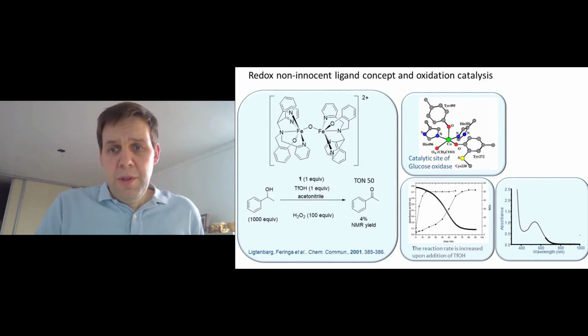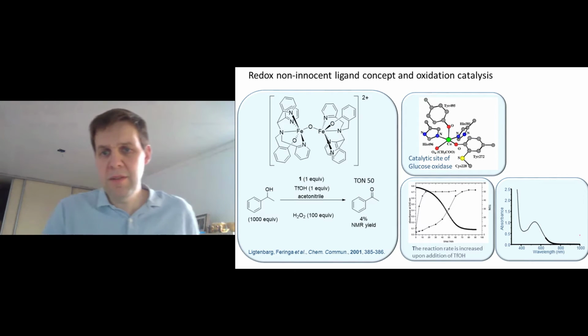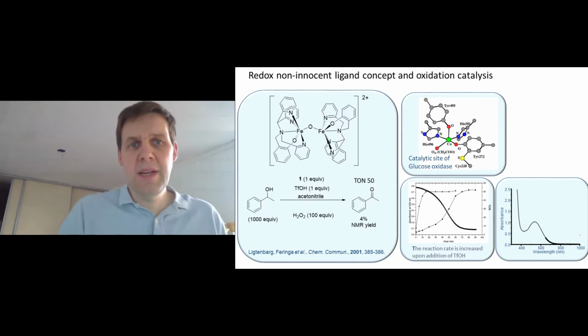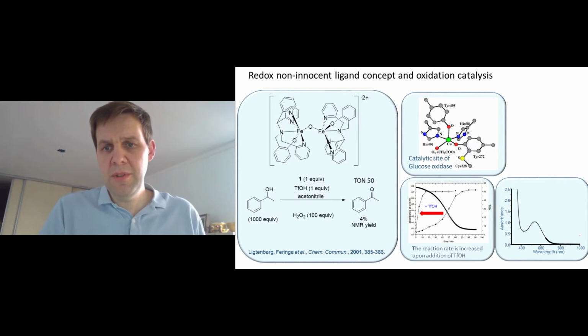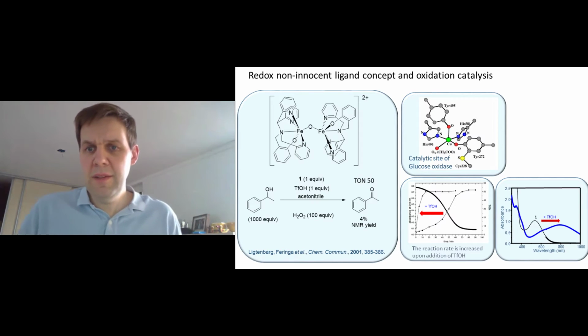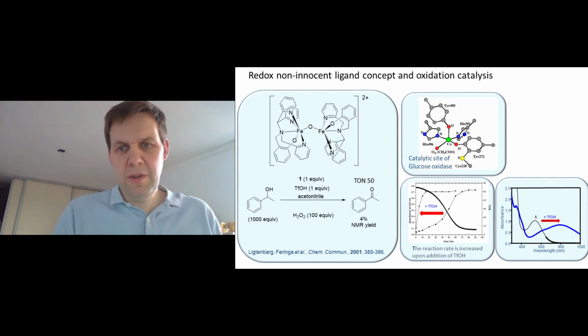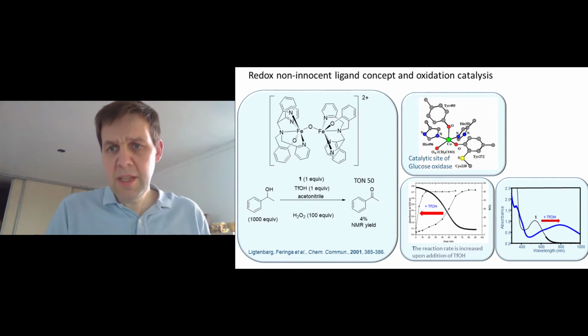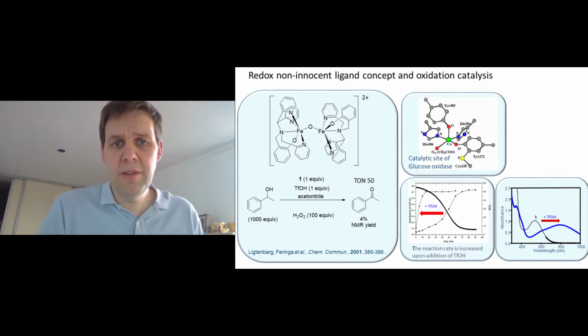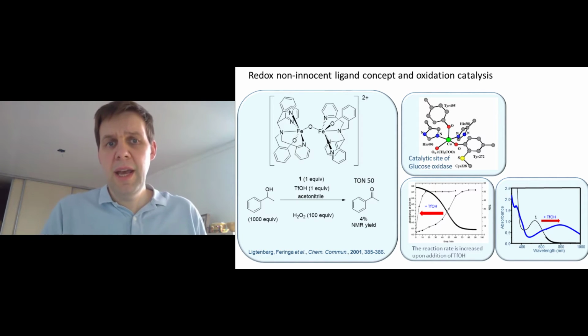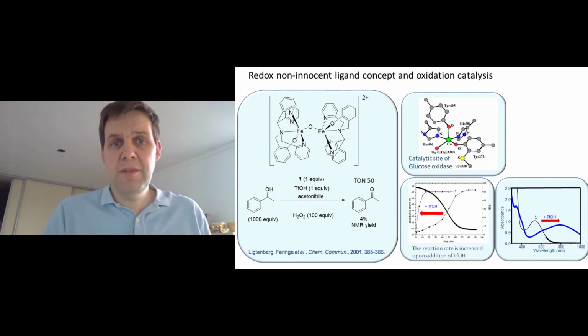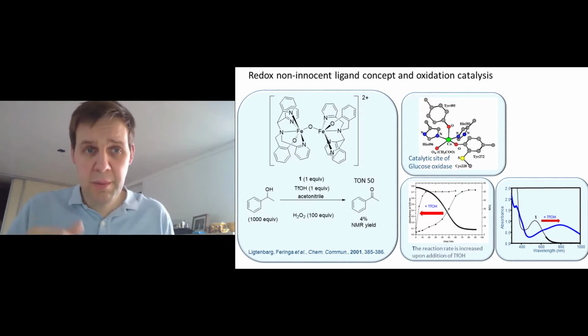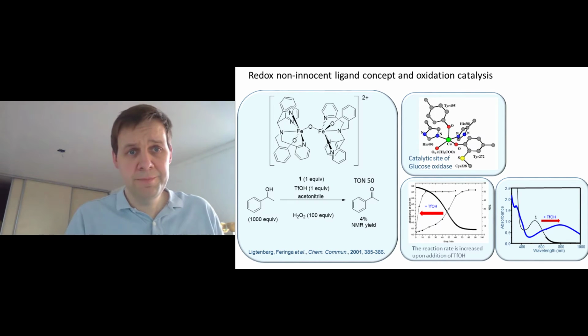what do you see in absorption? Well, here's the absorption spectrum of the iron complex. It's got an absorption around 590, 580 nanometers. And if we add acid, that absorption shifts and we get this very odd blue colored solution. And that gives an indication there's a change in structure of the compound upon protonation, and the complex then becomes more reactive. You can imagine if you put a proton on top of that oxygen between the two irons, it would be easier to break up the complex.